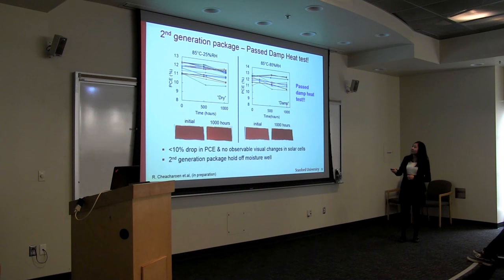And comparing how the solar cell does in dry heat with 25% relative humidity versus the one in damp heat, we see very similar degradation. So I would say that the package is holding off the moisture really well.